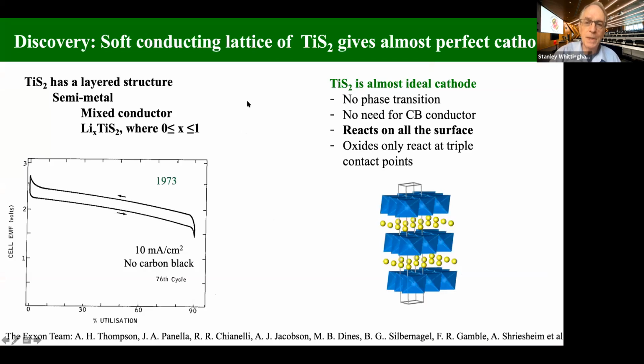So let's look at what was special about the layered sulfides we looked at. Initially, we were looking at these as superconductors. In fact, we looked at tantalum disulfide because by intercalating electron donors into the structure, we could change the superconducting transition temperature. Once we found out they were potential electrochemical devices, we switched to the lowest weight one, which is titanium. And it turns out this material, besides having a layered structure as shown here, these are the titanium disulfide sheets. In between these reside the lithium. And anybody who knows the thermodynamics knows that at ambient temperatures, entropy plays a role. So there's always some distribution of titanium from the titanium sheet down to a lithium sheet and vice versa.